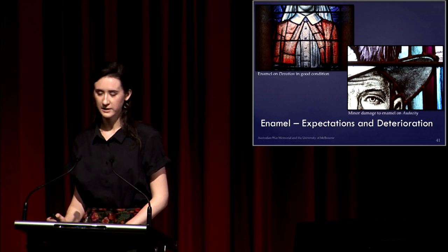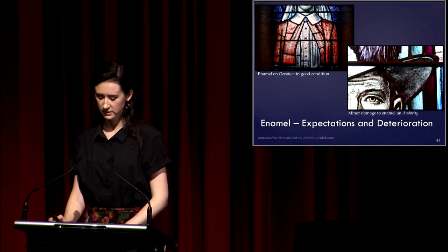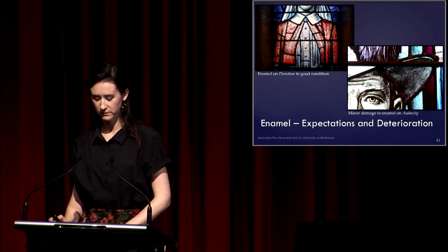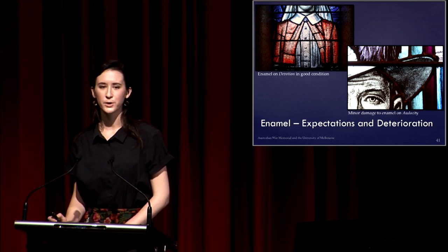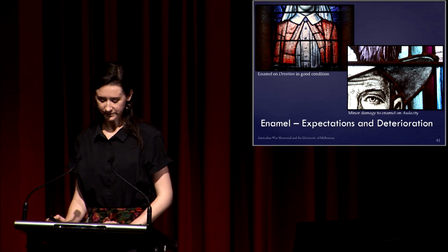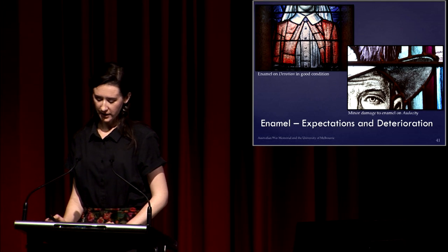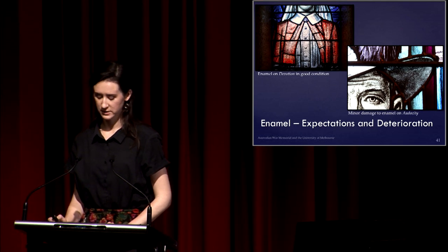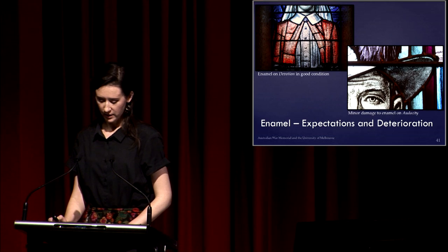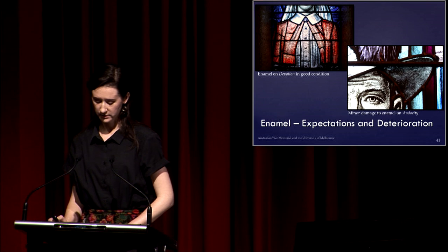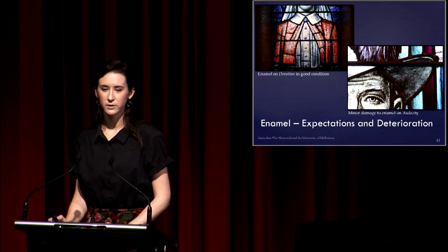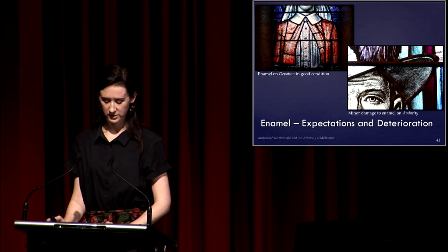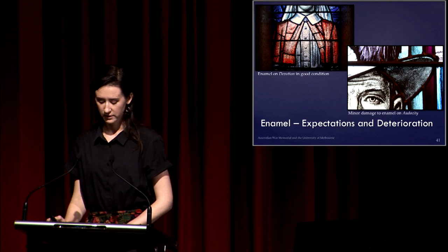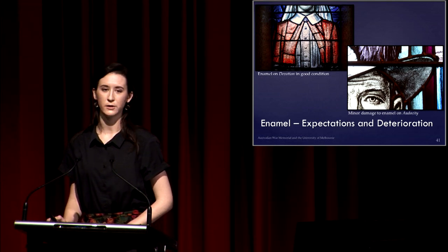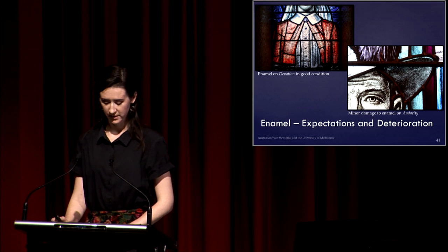Following the professional techniques they learned in the UK, the Wallers are gladly known to have used very stable materials in general, but also including the enamels. The chemistry of the paint on these windows was also analysed with XRF, and we found the presence of lead, iron, cobalt, and copper metal oxides, which would have been added as colouring similar to the glass, but also they will prevent the dissolution of soluble salts, which is the alkali.